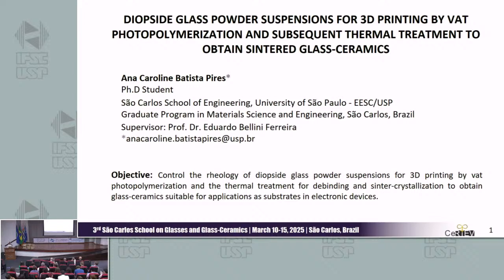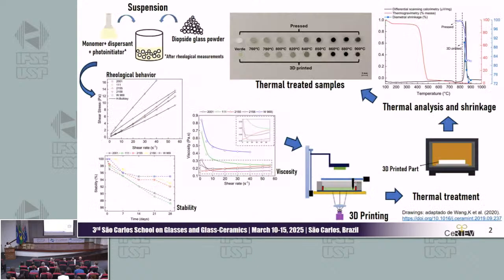In the poster, I will present my results about diopside glass powder suspensions for 3D printing, and the thermal treatment of the 3D printed parts to obtain glass ceramics for applications as substrates in electronic devices. For that, we prepare the suspensions and characterize the rheological behavior by measuring viscosity, shear stress, and stability. Based on this result, we choose an optimal condition to proceed with the 3D printing process. After that, the parts are thermally treated for debinding and sinter crystallization, followed by the evaluation of the shrinkage and visual inspection at the first moment.